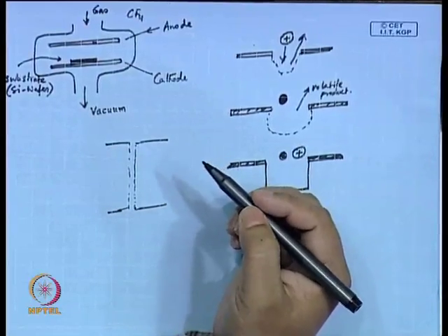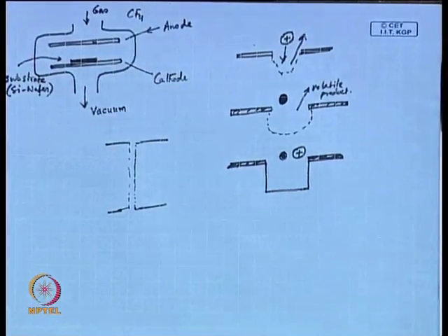That is an issue here, and this deep reactive ion etching is a very popular technique for doing this job. The way it works is that it is basically a physicochemical etching. However, in the case of a chemical etching, the reaction product that is formed is volatile, so it desorbs from the surface and diffuses back to the bulk.